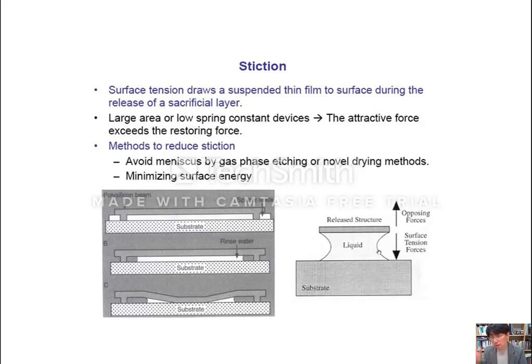There is surface tension that holds your structure to the substrate, and then there is an opposing force because this is like a spring, anchored from the side. So this is like a spring. Those two forces are balanced. But again, the middle is relatively softer compared to the edge. Okay, so that's why this surface tension pulls in the structure during the evaporation. Then when the liquid is about to evaporate, this release structure actually touches the substrate. Okay, so this is a big problem in MEMS fabrication because you want to have a freestanding beam.